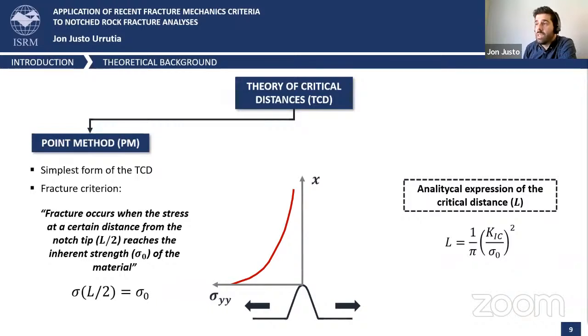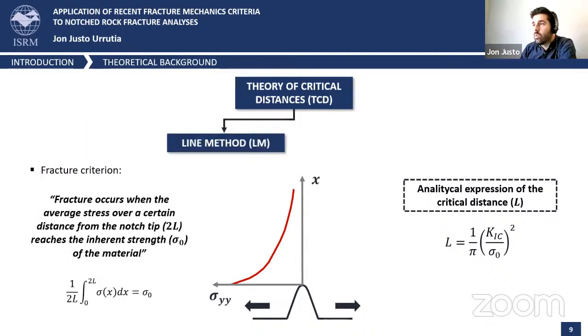So the first one, the point method, is the simplest form of the theory of critical distances, as it states that fracture occurs when the stress at a certain distance from the notch tip, which is equal to the critical distance divided by 2, reaches the inherent strength of the material. On the right of the slide, you have the analytical expression for the critical distance, which only depends on the fracture toughness and on the inherent strength of the material. In the case of rocks or quasi-brittle materials, the inherent strength can be assumed to be roughly equal to the tensile strength of the material. So in order to define this parameter, we only need the definition of the fracture toughness and the tensile strength of the rock.